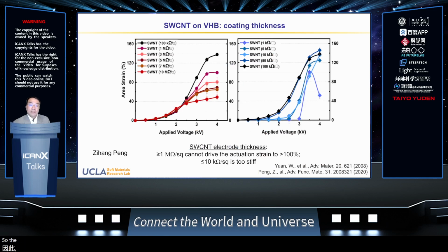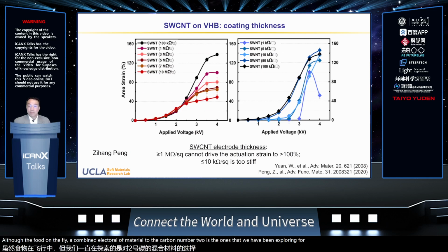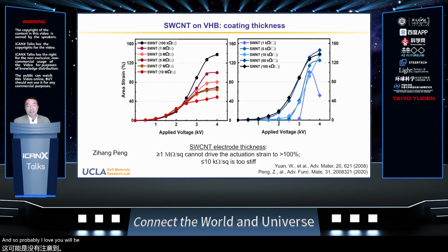So the salt water and the gel electrolyte both work well. But we have been trying a totally dry, compliant electrode material. The carbon nanotube is the one that we have been exploring for a number of years now. Carbon nanotubes can be dispersed in a solvent and then sprayed, and depending on the spray thickness, you can have different sheet resistance.